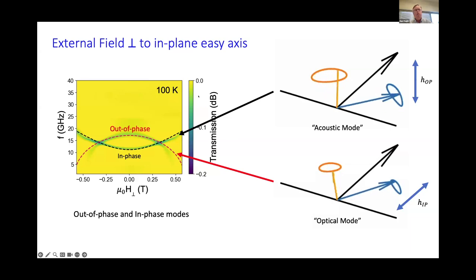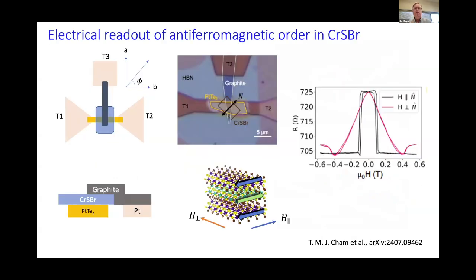In the experiments on smaller scale devices, we'll mostly work with magnetic fields perpendicular to the z-axis, and we'll be detecting the optical mode, because that's the one that changes the relative orientation of the spin sublattices and gives magnetoresistance signals. Okay. So once you try scaling things down to much smaller size scales, this is the geometry we have in mind. It's a 3-terminal tunnel junction. On the bottom is a metallic conductor layer, platinum telluride, chosen both because it's metallic, which reduces the overall tunnel junction resistance, and it has reasonably strong spin-orbit coupling, so we'll be able to apply spin-orbit torque here in a few slides. The middle layer is a bilayer of chromium sulfur bromide, an A-type antiferromagnet, ferromagnetic within each plane and antiferromagnetic between them. So we have a 2-layer antiferromagnet as our barrier, and then the top layer is just graphite for making easy contact. In DC measurements, we can measure how the resistance changes as we change the relative orientations of the spins in the spin sublattices.